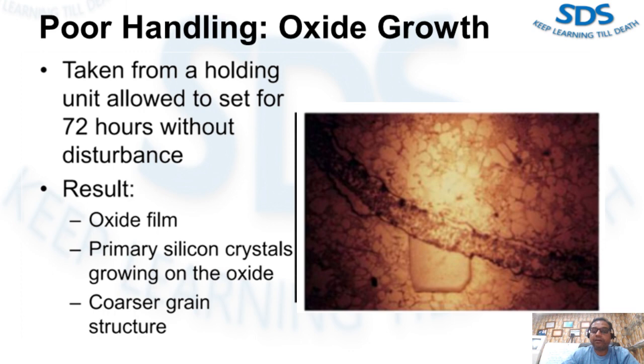If time allows, the furnace should be brought up to 1350 degrees Fahrenheit, cleaned thoroughly, flushed, and drossed off. If electric globar holding units are used, this cannot be done — those furnaces should be emptied and refilled. The metal from the holding unit should be sent back to the central melt area for reprocessing.